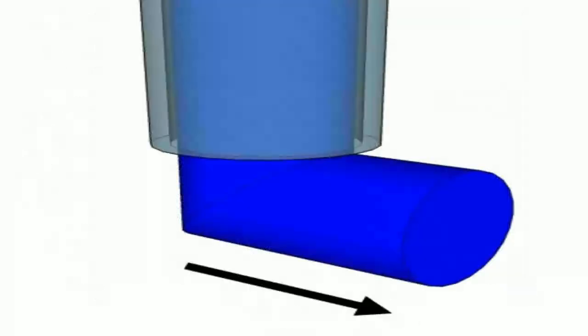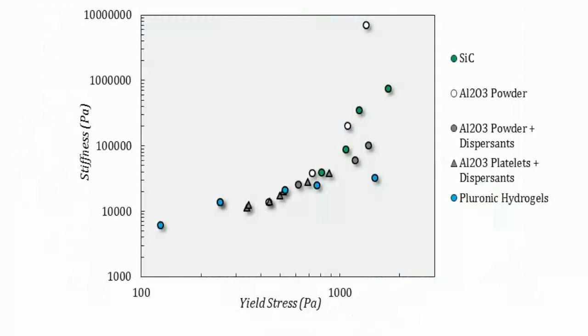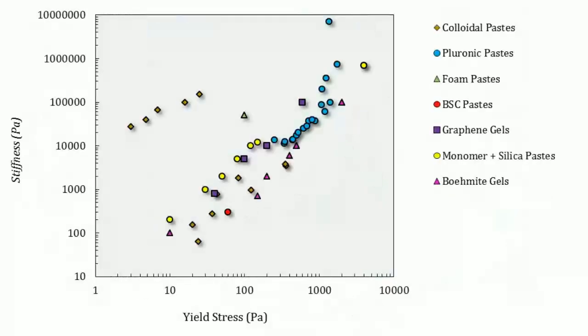Yeah, the source addresses that too. Generally, robocasting is limited in resolution compared to other methods, like lithography-based ceramic manufacturing, or LCM, which can achieve much finer details. Why is robocasting limited? Well, the minimum feature size is typically tied directly to the nozzle diameter you're extruding through, and that nozzle needs to be reasonably large, often 200 micrometers or more, just to handle the thick particle-filled paste without constantly clogging.